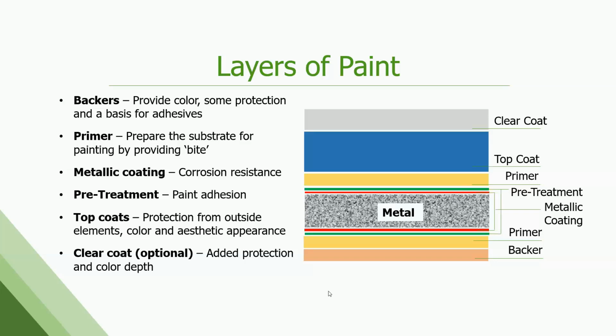We do paint the back side, the underneath of the strip, even if it's not going to get exposed or be seen in the final application. And we do that for a couple of reasons. It's often overlooked, but it plays an important role. It helps protect for corrosion once it's installed. It also helps protect the coil when you wrap it back up. If you had a metal-only side wrapped up in that coil against the top coat, it's under very, very high tension, and you can cause damage to the painted side. So you like to have paint against paint. And work is done to make sure that those two are compatible because they're going to be in contact with each other in coil form under very tight pressure.